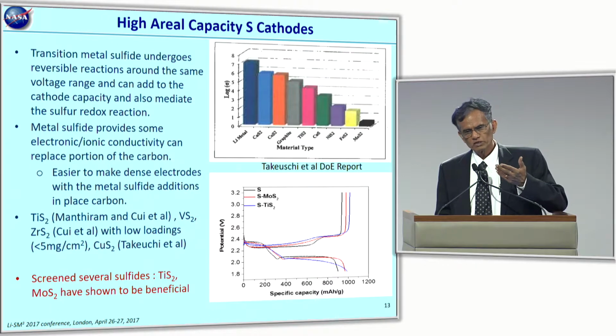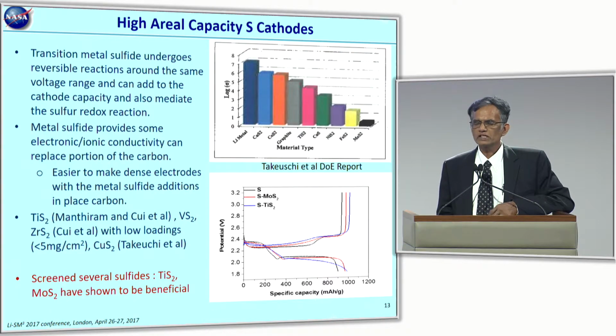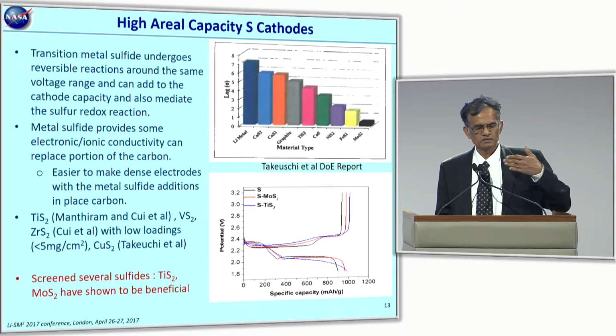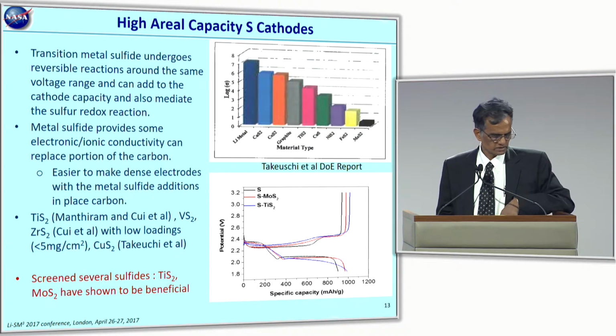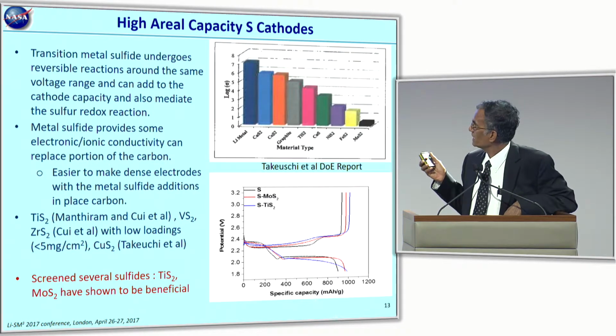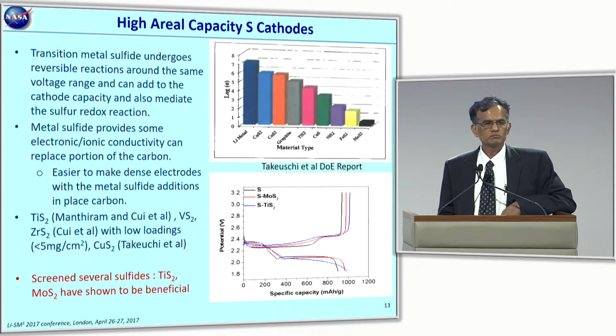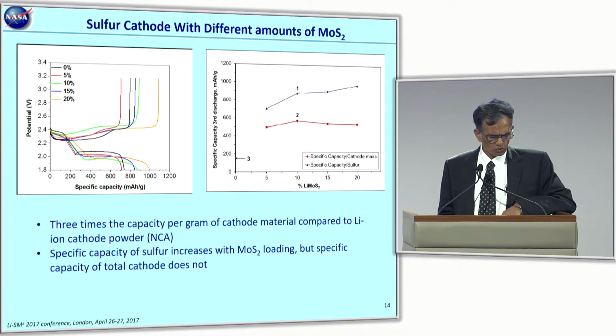And TiS2 has been reported by many people, but moly hasn't been looked at by anyone. So that actually gave us two advantages. One is it was easier for us to make the dense electrodes, and there is also some capacity being provided by MoS2 because it's an extremely reversible cathode system. So by adding those things, as you can see here, typically you don't see any change at all in terms of the voltage characteristics of the sulfur cell. And so we focused a little bit more on the moly.